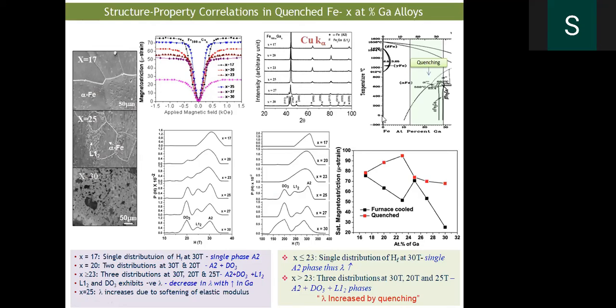fortunately, since all the phases are going to be ferromagnetic, we adopted the Mossbauer spectroscopy technique. Not to quantify, but to qualitatively tell what the different phases are, because different phases have different magnetic moments. So we have done the Mossbauer, and the hyperfine distribution spectra is shown here. If you see the variation with respect to the magnetic field and the distribution spectra, the 17 alloy showed a single phase, which is only because of the alpha Fe. But as we go to 30, it shows alpha Fe, that is the A2 phase. We have L12 phase and DO3 phase, and all the observations we are seeing closely match the microstructure.